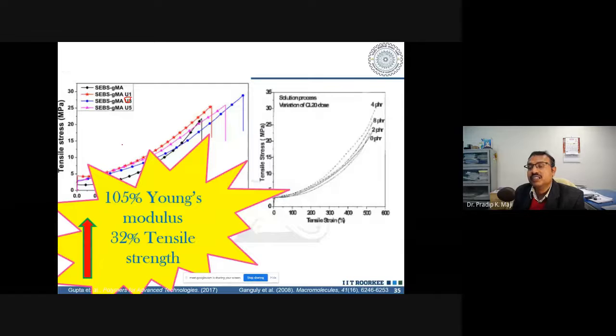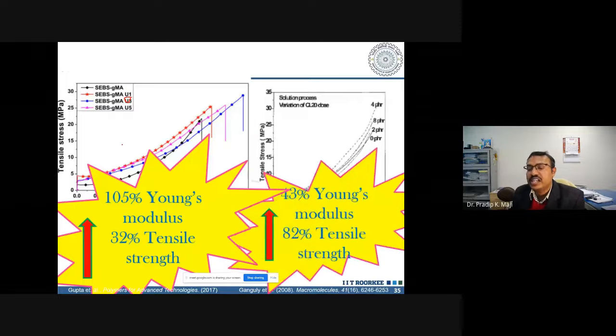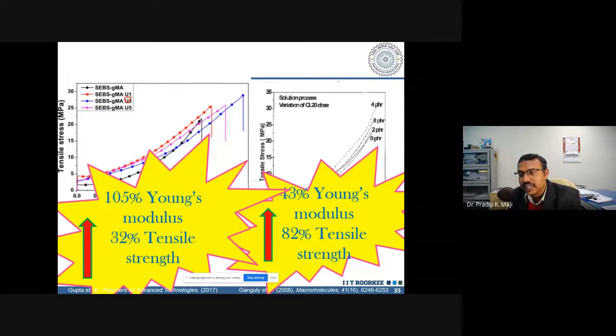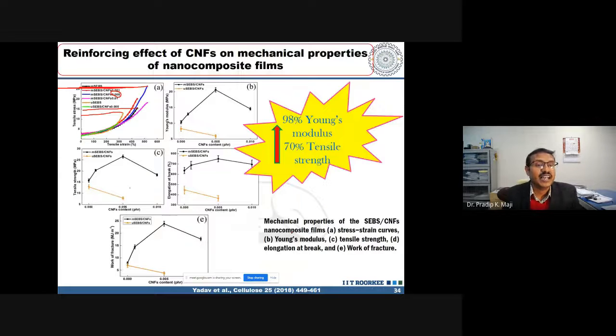If I compare with cloisite 28 clay, at 4 phr clay it is giving 43% Young's modulus increment and 82% tensile increment. So comparing cloisite clay at 3 phr and cloisite 28 clay at 4 phr, our system is able to enhance the material property by 98% and 70% with only 0.005 PHR. Try to realize, that's why with minimum amount of material we can enhance the mechanical property.